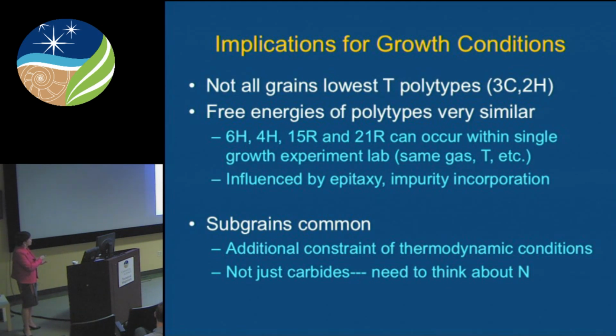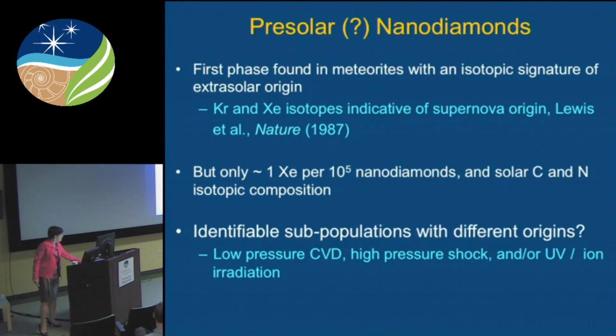And it's affected by epitaxy of one grain on the other, the nucleation of one grain and growth on the existing surface, and the incorporation of impurities such as aluminum and nitrogen. We also see from these pre-solar grains that subgrains are really common. So we saw the iron nickel rich grain and the aluminum nitride grain, and these provide an additional constraint of the thermodynamic conditions. And we need to go back to the phase diagram and look not just at the carbides, but nitrides as well for constraining the environment.